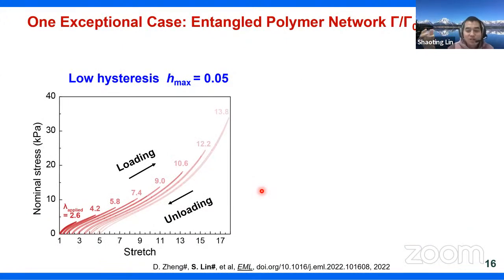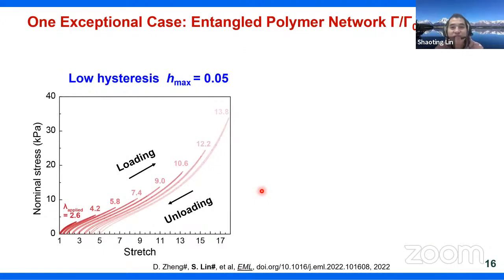So far, this is nothing special, because especially for metals and plastics, people know that introducing bulk hysteresis will enhance toughness. But here is something interesting. We found an exceptional case. What we found is that in entangled polymer networks, the toughness enhancement does not rely on a large hysteresis loop. So here's the result.